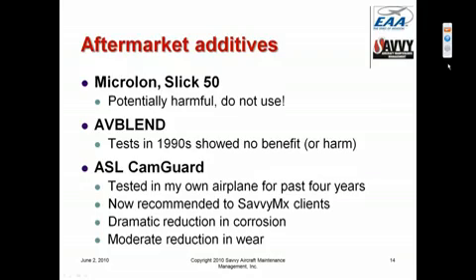When it was first introduced, we did a bunch of tests in some piston twins where one engine was treated with AvBlend, the other engine was not treated, and the engines were on a very rigorous oil analysis program, and we literally could not tell which engine was the treated engine. We saw no reduction in wear metals, and the primary claim to fame of AvBlend is it's supposed to inhibit wear. We just didn't see it in the tests. On the other hand, we've never seen any evidence that AvBlend does any harm to engines.